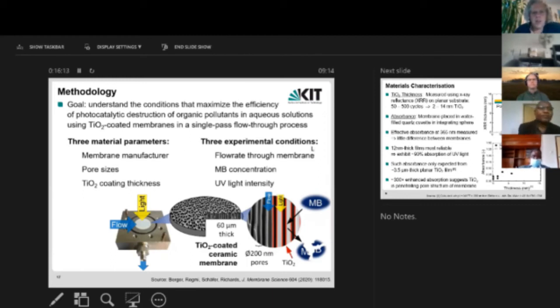And then on the right, we're going to look at varying 3 different experimental conditions: the flow rate of the feed flowing through the membrane, the concentration of methylene blue, and the intensity of the ultraviolet light. Bringing all that together in one graphic at the bottom, you have your light coming in on the stainless steel cell, which you wouldn't normally see. This is the bottom half of it; it would normally be sealed. In there is your membrane with the cylindrical pores. It's now, hopefully, as shown on the right-hand side, being coated with red, which in this case would be the titanium dioxide, enabling photochemical destruction of a methylene blue molecule.